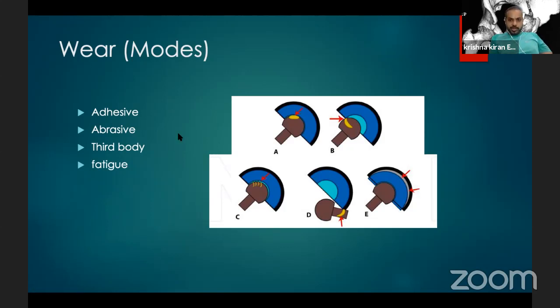The other thing which can happen is a slight subluxation of the hip, which always happens. Whenever there is a transition from a swing phase to a stance phase, or a stance phase to a swing phase, there is micro separation of the hip, and the behavior of the bearing surface during micro separation is an important consideration while choosing the bearing surface. The second is third body wear or abrasive wear, which we talked about, when you have particles like bone pieces or metallic pieces inside the articulation.